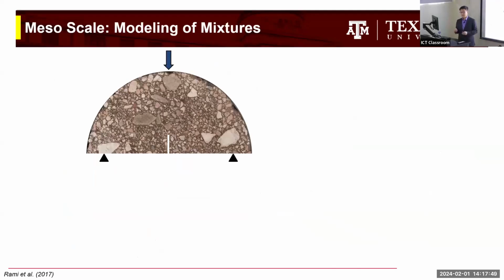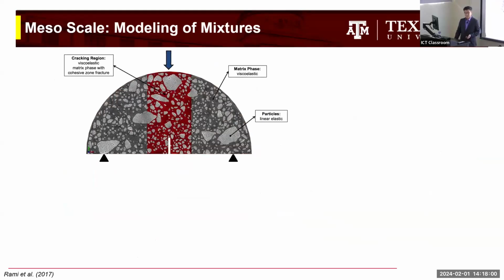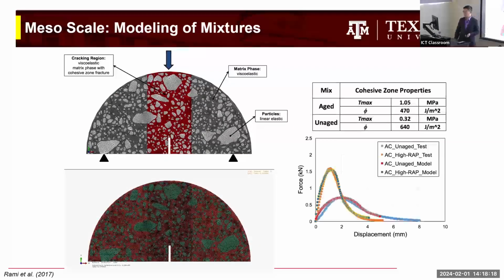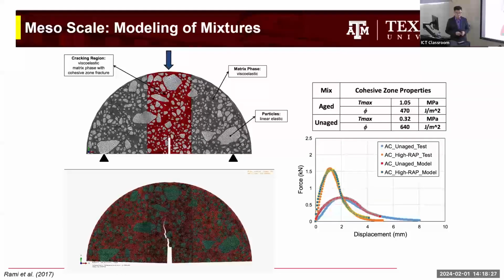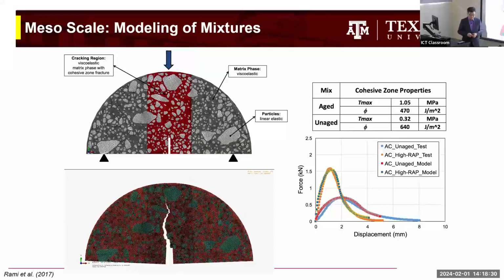So with that fracture model, we can now apply it to our civil engineering testing and application. Like SCB, we do SCB testing a lot. And then we can make our own finite element model, and provide the right material properties, viscoelasticity, elasticity for rocks, and the cohesive zone fracture parameters we found from the calibration process. And then we can simulate using an office computer instead of conducting the laboratory testing, like a virtual testing we can do with our computer package.